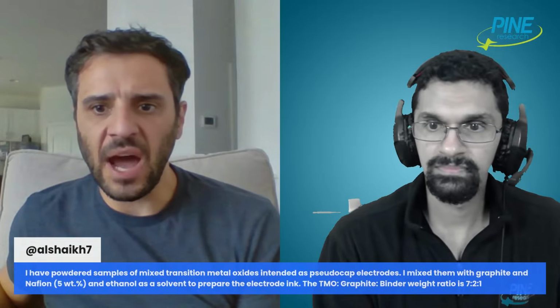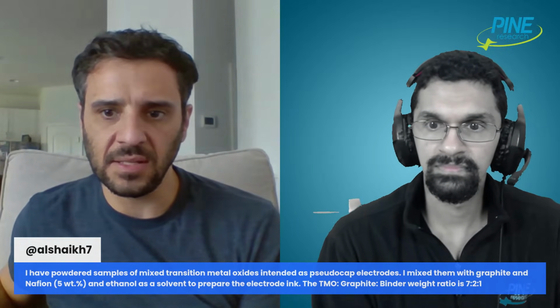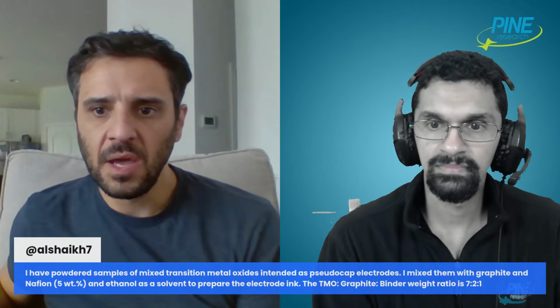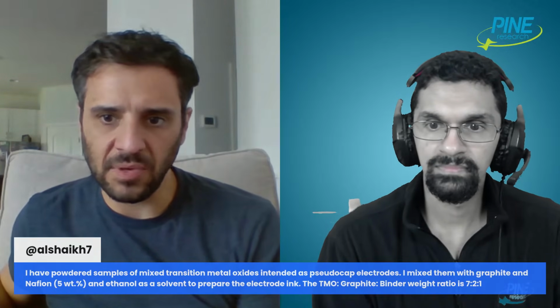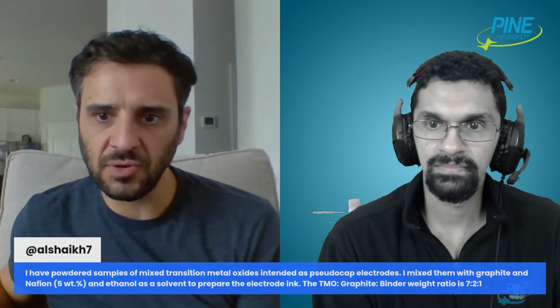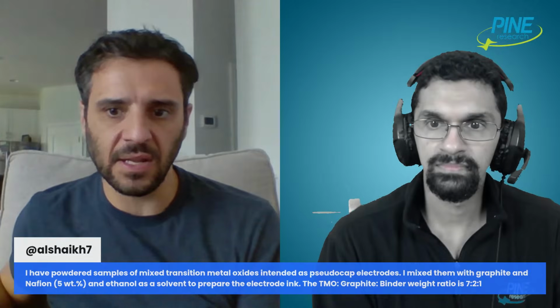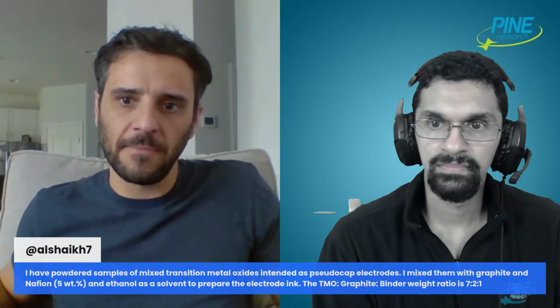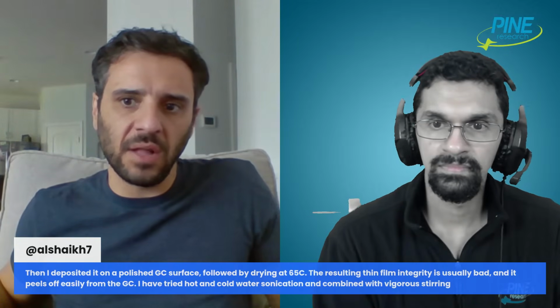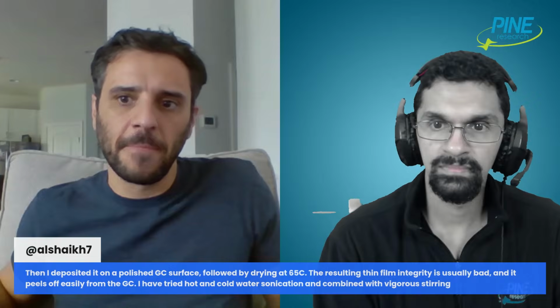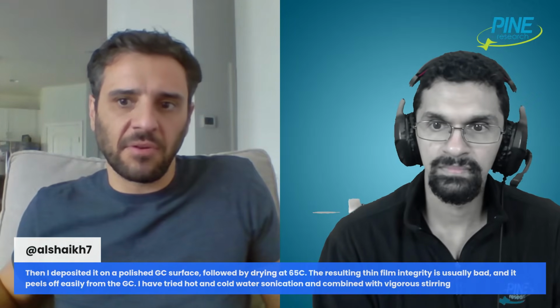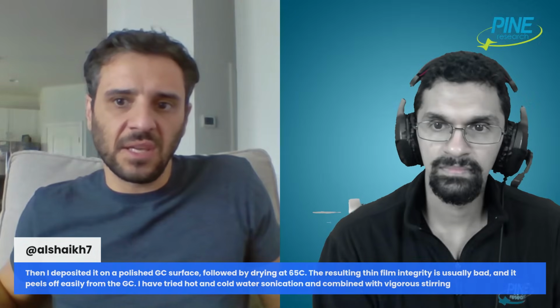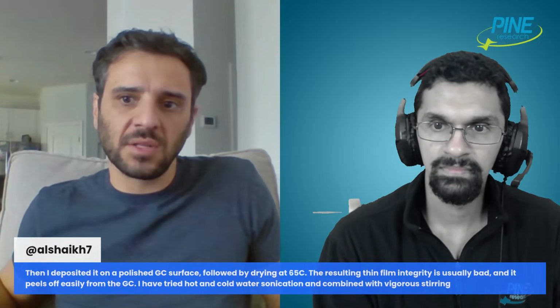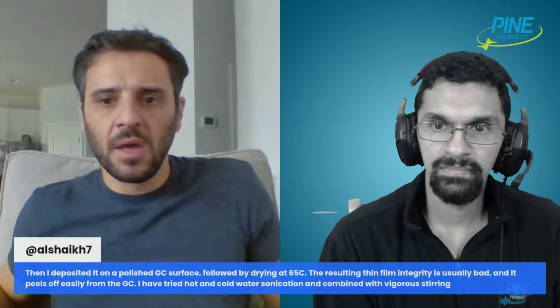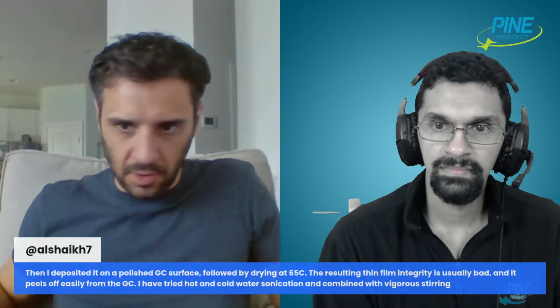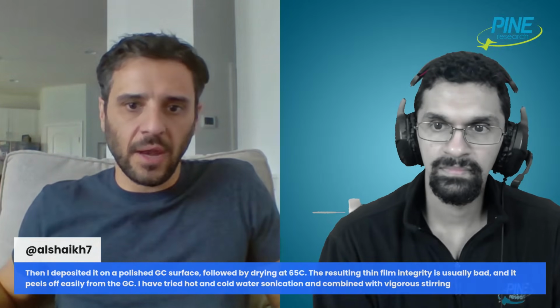They said, I have powdered samples of mixed transition metal oxides intended as pseudocapacitor electrodes. I mixed them with graphite and Nafion, 5 weight %, and ethanol as a solvent to prepare the electrode ink. The transition metal oxide to graphite to binder weight ratio is 7 to 2 to 1. Then I deposited it on a polished glassy carbon surface, followed by drying at 65°C. The resulting thin film integrity is usually bad, and it peels off easily from the glassy carbon. I have tried hot and cold water sonication combined with vigorous stirring. So the question was basically, how do I do this better, or very vaguely, what's going on.